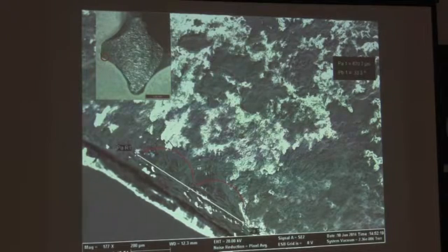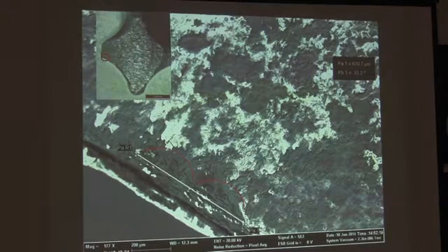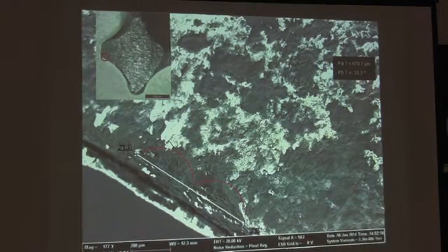Those are the two pit corrosions. Here you cannot see fatigue because the magnification is very low and some oxidation phenomena make it impossible to see fatigue. And we see clearly two corrosion pits with a depth of 100 microns and a width of 300 microns.